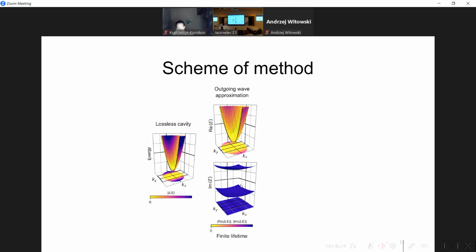Now, using the Green function, we found the solution in the outgoing wave approximation, and when we consider this outgoing wave solution, we get an energy which is a complex number, where the real part corresponds to the energy of the emitted photon, and the imaginary part corresponds to the lifetime of the photon in the cavity.